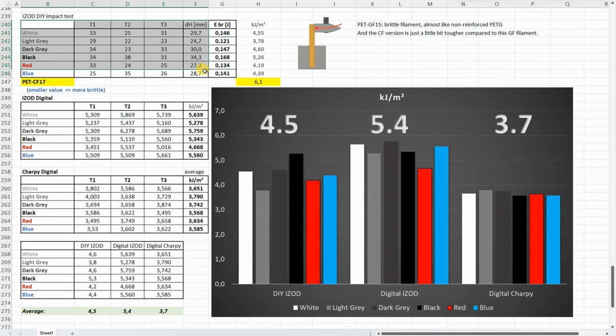Results from my DIY Izod impact tester, Izod digital, Charpy digital, summary for all 3 which you can see on this graph, and these are the average values which you can see here. And for the brittle filaments, this is a typical ratio between DIY Izod and digital Izod testing machines. And this is important because in the future I want to stop doing my DIY Izod impact testing only using the digital machine. And overall this filament is quite brittle, almost like some non-reinforced PETG. And the carbon fiber version is slightly tougher compared to the glass fiber version.